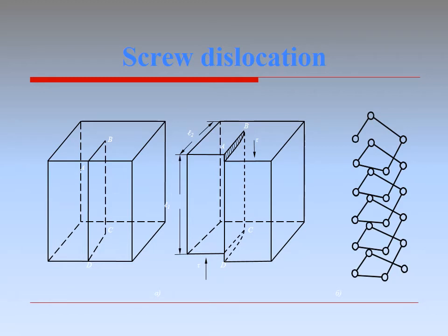Dislocation cannot end inside the crystal. Consequently, the dislocation line may close or terminate within the crystal on its surface. Some parts of dislocations are edge or screw, but much of it is neither parallel nor perpendicular to the shear vector. Such a dislocation is called mixed.